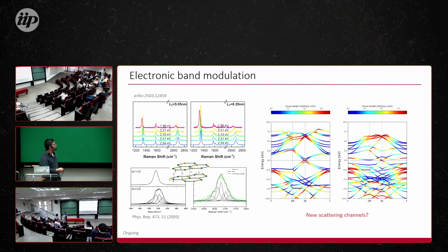So what I want to understand is the scattering mechanisms, channels, or pathways, considering the electron going from here to here. If you consider, for instance, phonons, the 2D band and the D band are actually phonons involving scattering from K to K prime points. And this one here is just the in-plane vibrational modes of the carbons, so it can be in the X and Y directions. We can combine those things with DFT to try to figure out what's happening to the system. Basically that. Okay, thanks.